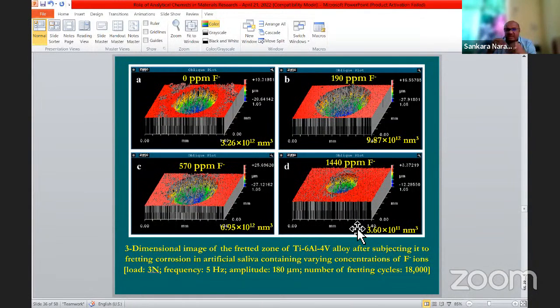So fluoride will attack the titanium. But during that fretting corrosion, a lot of debris is generated and sticks onto the alumina ball. So the contact configuration changes from an alumina ball against titanium to a titanium-coated alumina ball against titanium. When the counter body is coated with titanium, the titanium is rubbing against titanium, so there won't be much removal of material. That is why the wear volume decreases.